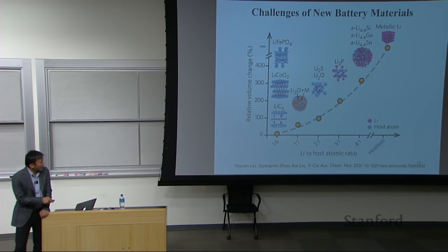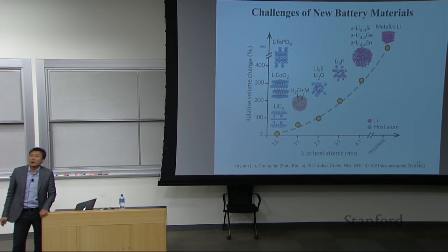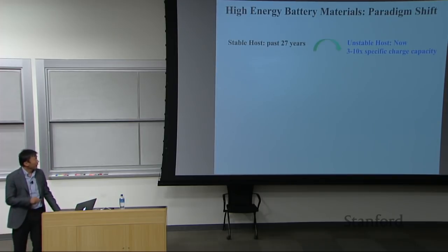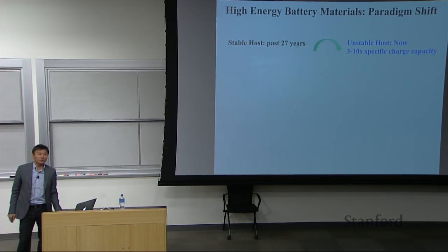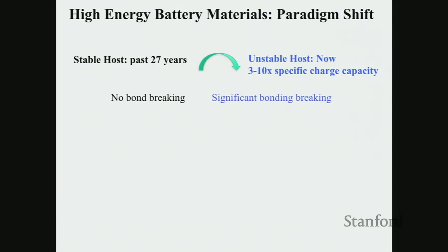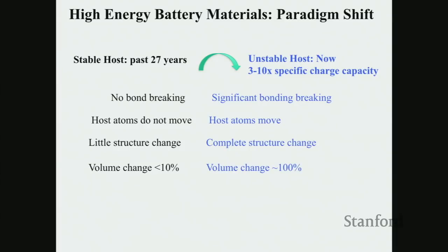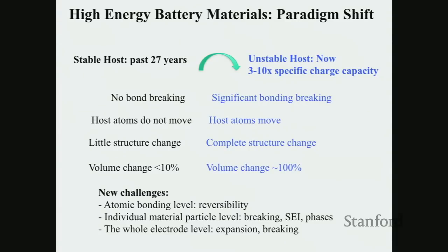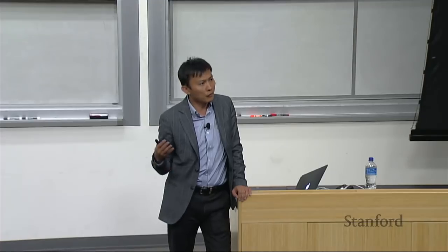As soon as you store a lot of lithium into hosts, these different materials really start to show up. However, the amount of volume expansion increases tremendously. This is one of the fundamental reasons why using high capacity material is so difficult. It causes the following problem. For the past 27 years, we have had stable hosts to host this lithium. New materials can store a lot more lithium, but have the problem of chemical bond breaking. So many lithium and so many electrons coming in and stored in the structure, you have bond breaking. Atoms are moving all the time in these host materials. Very large structure change, big volume expansion. So you need completely new ideas. How do you handle the materials issue in order to make these materials workable inside your phone, inside your car?